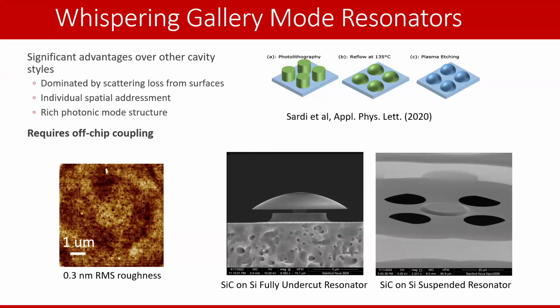This is also because, with the exception of Noda's group in Japan, making photonic crystal cavities that are really high quality factor is very difficult. It's not easy, and it's also extremely difficult to get it to match simulation. So this is another reason why we chose whispering gallery modes: the geometry is very simple. It's a circle, and your loss is basically dependent on just the scattering loss from the surface roughness and the bending radius. And material losses, which, as we said, silicon carbide has been developed to the point at which the material losses are relatively negligible. So as a result, we developed extremely smooth whispering gallery mode resonators using a photoresist reflow process.